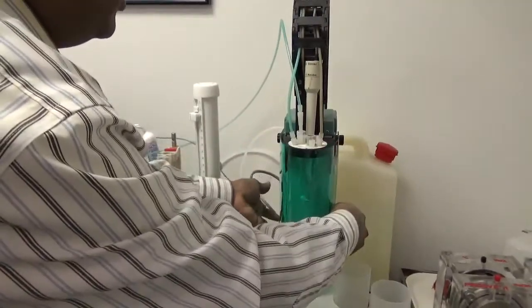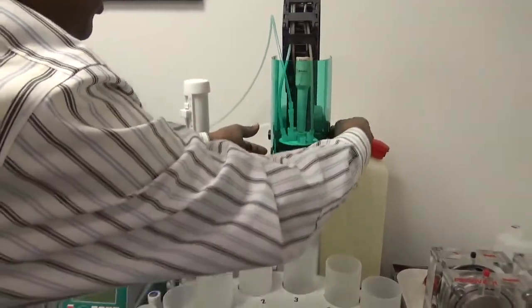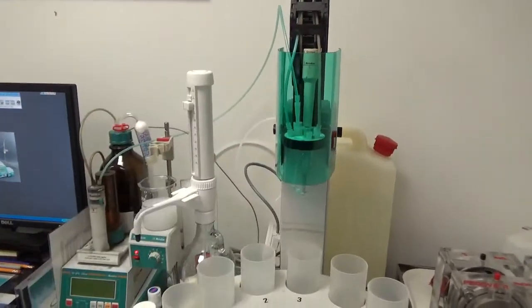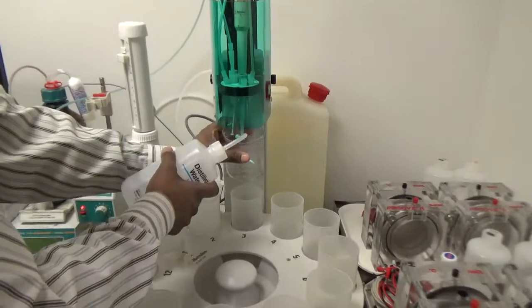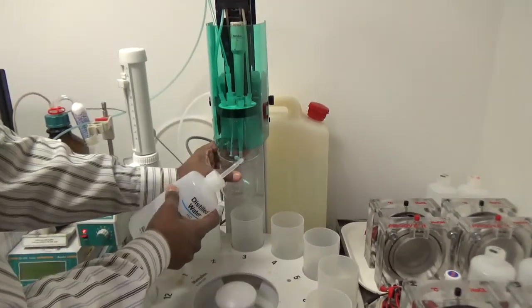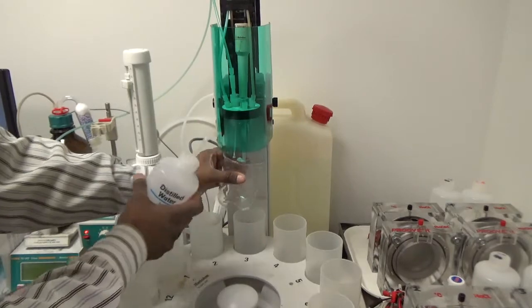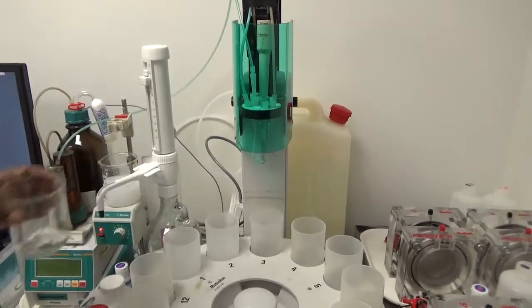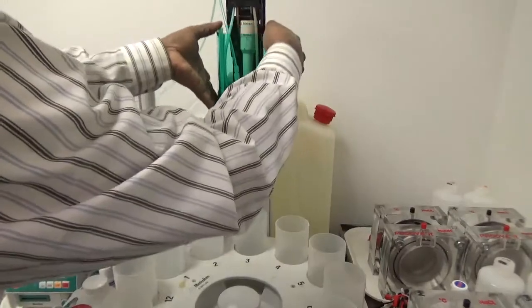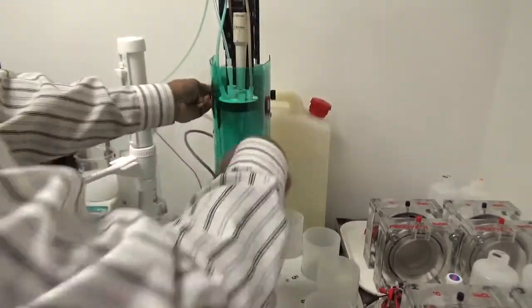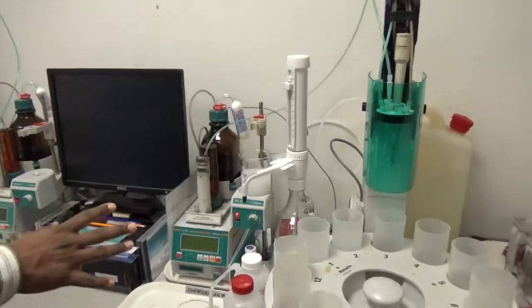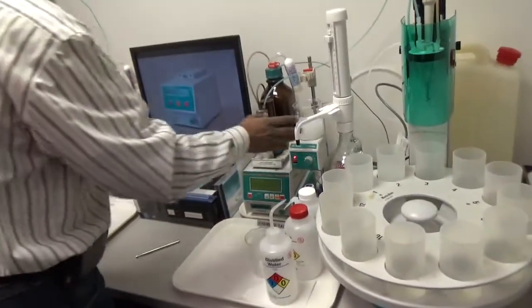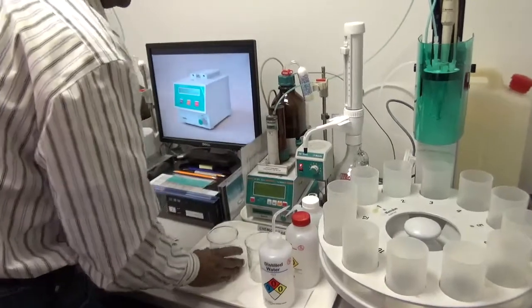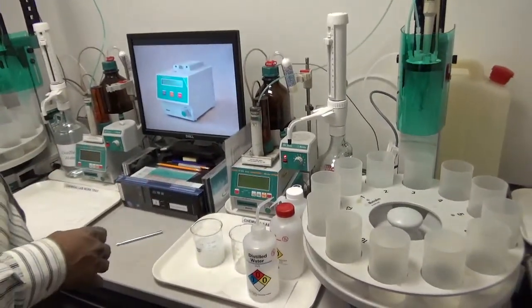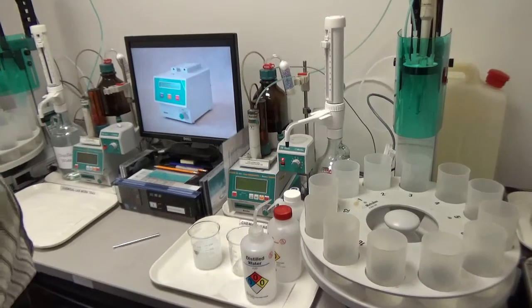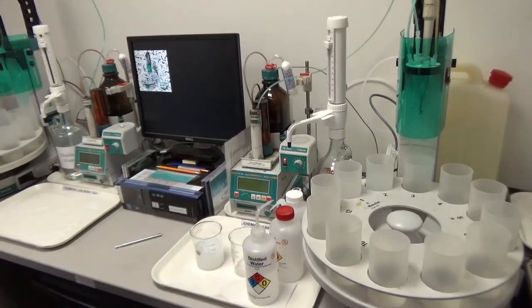Sometimes we remove the splash shield, and if there is some salt precipitated on the tip of the stirrer, we just use the distilled water to clean the tip of the stirrer. And then we bring the splash shield down and stay there for the next set of samples to run. So this is how we do the automated titration or manual titration, depending on the small volume or large volume samples of concrete for water soluble or acid soluble chloride analysis.